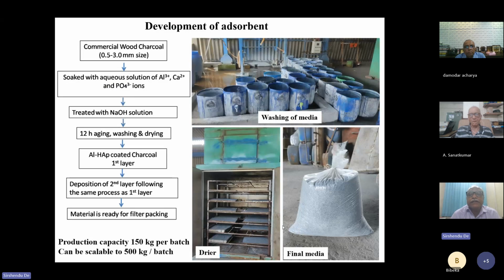We call this material aluminum HAP carbon, and this is a commercial production unit where 150 kg per batch is produced, and this can be scalable to 500 kg per batch to even 5,000 kg per batch. Here we do not require any high pressure, any acid, any alkali, or any heat treatment. These reactions occur at normal temperature and normal pressure using commercial grade chemicals. Since we are producing the carbon scaffolds in millimeter size, they are granules. We are not producing powder. Ultimately, we are producing the granules, and this is the final media that is produced.